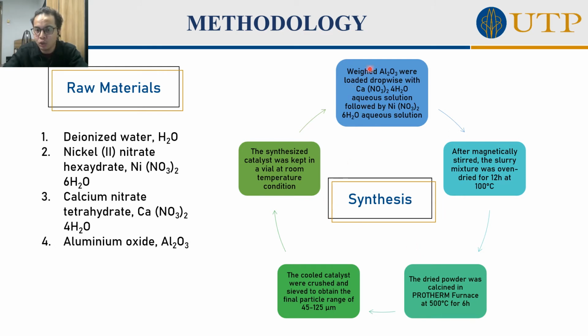So initially, we are going to weigh alumina and load it dropwise into the calcium aqueous solution, followed by nickel aqueous solution. The resulting mixture is magnetically stirred, and the slurry mixture was oven dried for 12 hours at 100 degrees Celsius. After that, the dried powder was calcined in a furnace at 500 degrees Celsius for 6 hours, and we cooled down.